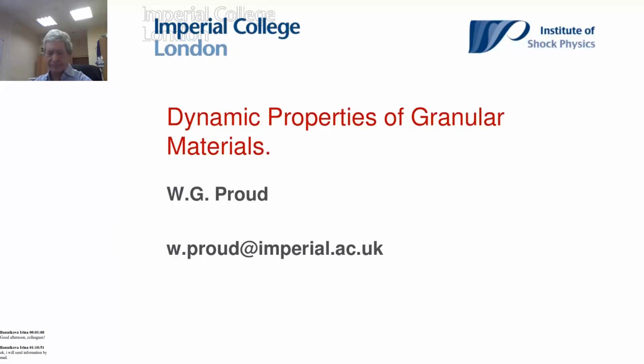Now, for the American Ceramic Society, this is a way of getting a fracture energy from the system. But from an experimental viewpoint, what they're doing is introducing some micro damage, which allows the fracture to nucleate in a consistent fashion in order to get their consistent data. So I think that is the kind of area where attention needs to be paid, because there is a lot of data out there based upon these types of tests where the sample has been preconditioned to fail in a certain way that it probably would not do naturally.